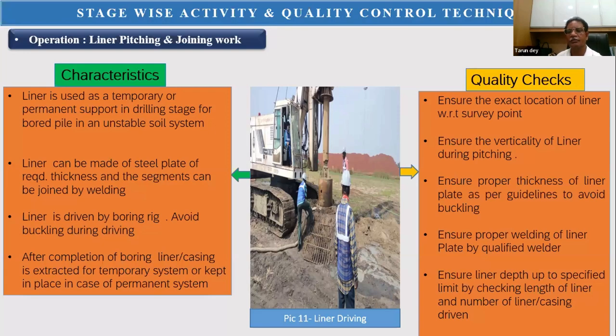So in this process, what you do, ensure the pile point with respect to the survey, this casing should be vertical. There is a limit for the verticality, 1.5%. It should be in the right position. There is a positional deviation tolerance also allowed. Then ensure proper welding of the plates, thickness of the plates. Normally it starts with 6 mm, could be 8 mm based on the diameter and the stiffness required.